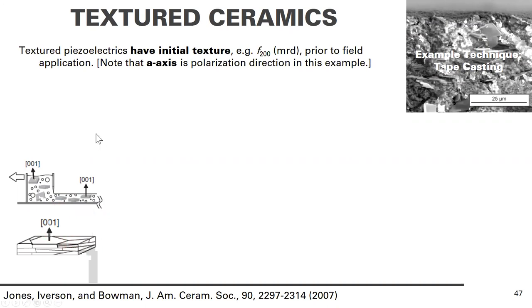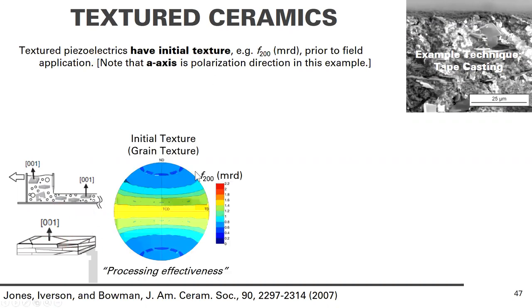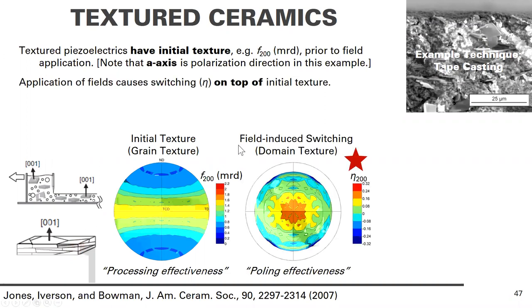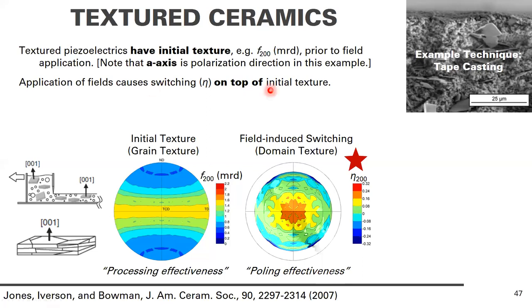Now, in this case, the initial material has an initial texture, and that's represented as this pole figure here. So the possible polar axes are oriented in the plane of the sample. Now, what we're going to do is take a cut from the sample and apply a field in the plane of this sample, and then characterize the field-induced switching effects. So the application of fields causes switching on top of the initial texture. And that switching can be represented over here as eta, the degree of ferroelectric switching that has occurred.